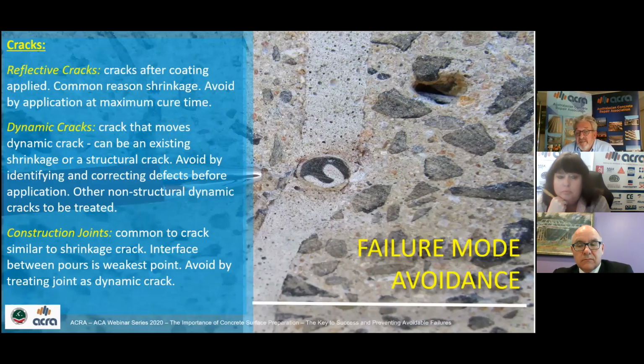Cracks. When concrete's poured, they don't get the cracks out of the concrete that's actually poured. Reflective cracks occur generally after the coating's applied. The most common reason for the concrete to crack is shrinkage, which takes place over time. Around about 44% of shrinkage occurs within the first 28 days of the concrete being poured. Most new construction projects are on tight schedules, many times insisting on concrete cure times of less than 28 days, which is the most commonly specified cure time.